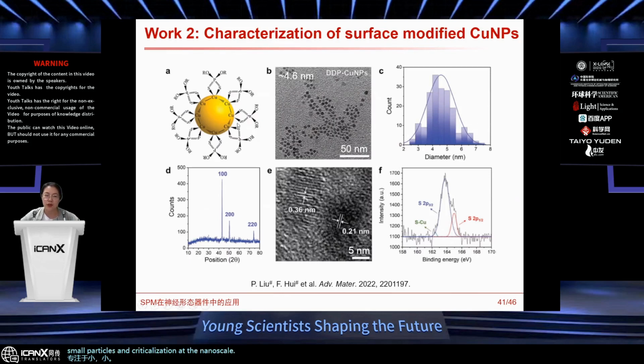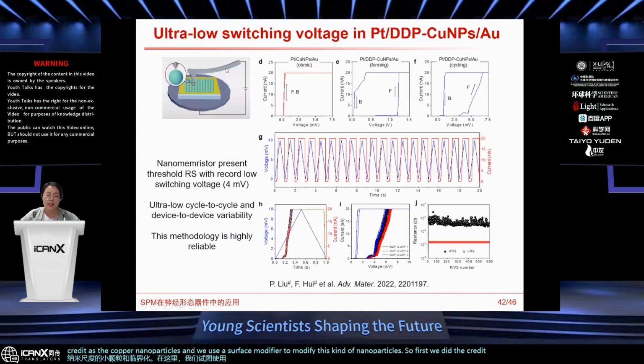And here we are trying to characterize the copper nanoparticles, and we use a surface modifier to modify this kind of nanoparticles. We did the characterization, and then we use C-AFM to characterize it, and we have observed that in such structures, we have seen very ultra small switching voltage, which is 4 mV.